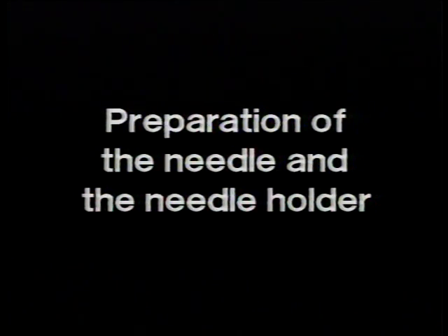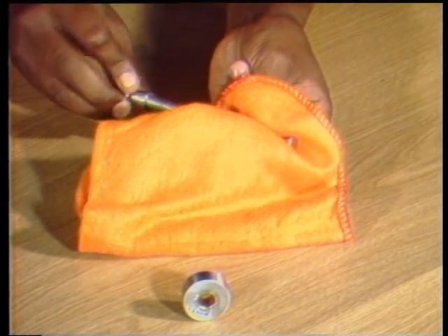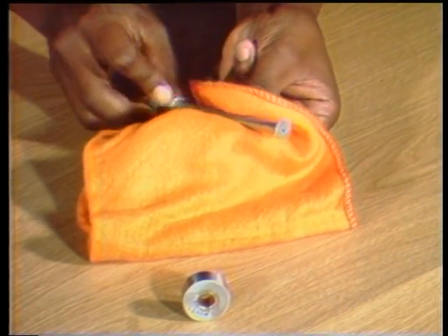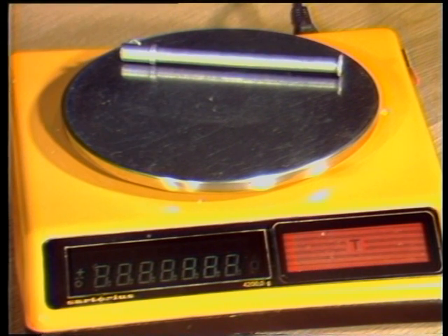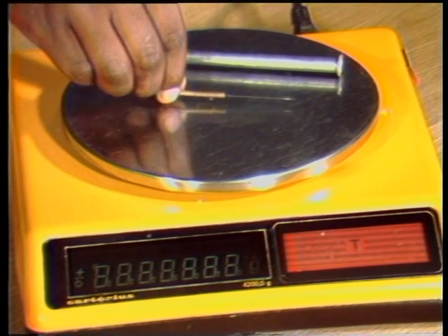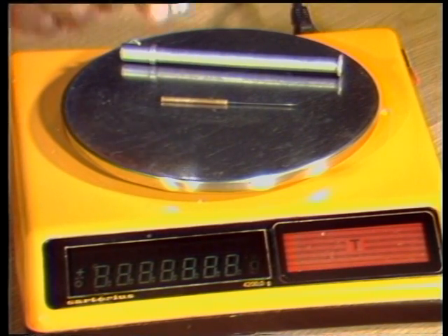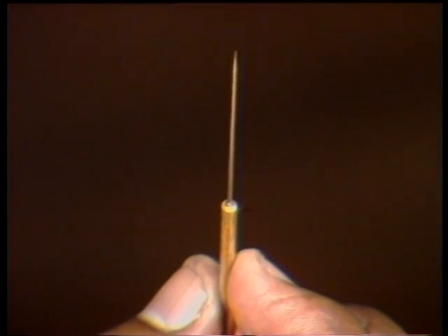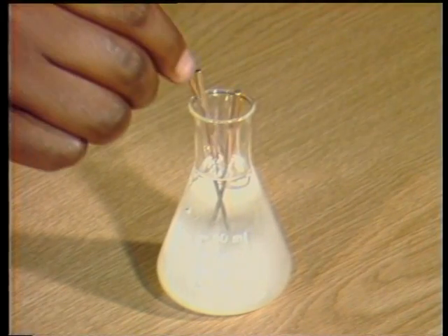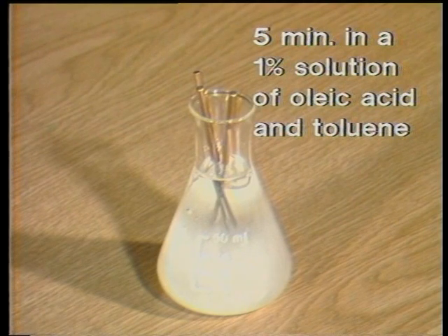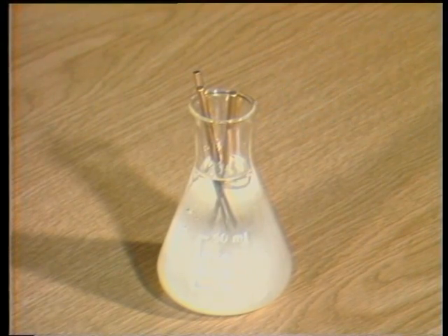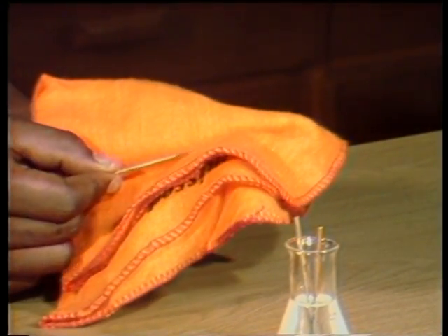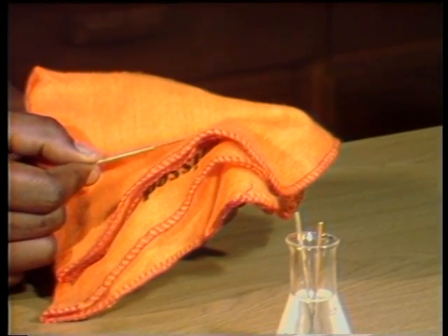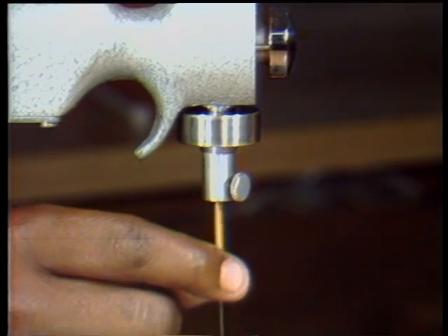Preparation of the needle and needle holder. Clean the needle holder. Ensure that the holder, penetration needle and weight together total 100 grams. Examine the needle for defects. Clean the needle by immersing for 5 minutes in a 1% solution of oleic acid and toluene. Dry the needle. Assemble the penetrometer.